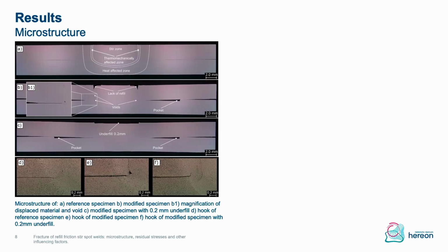And with F, we see the hook configuration of the modified sample with an underfill of 0.2 millimeters, where we have an upbending hook, which is not particularly good for fatigue results.